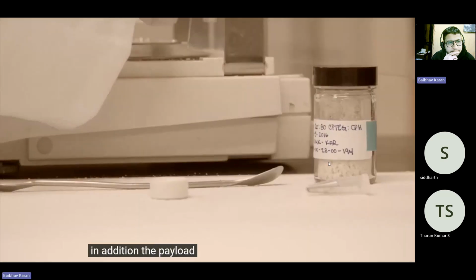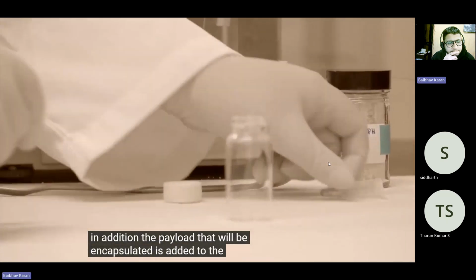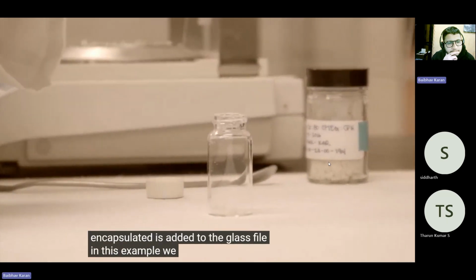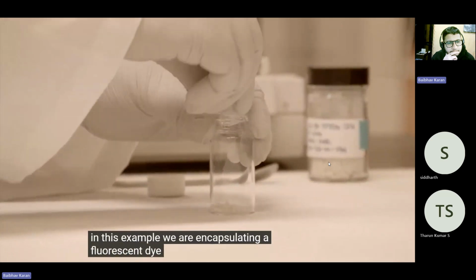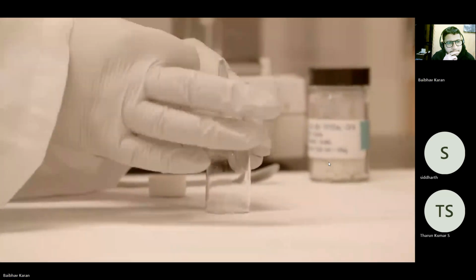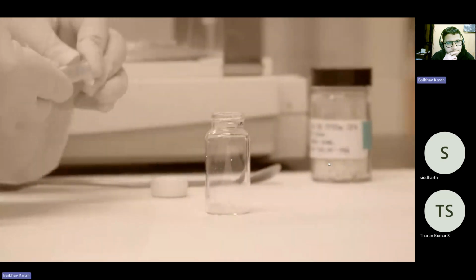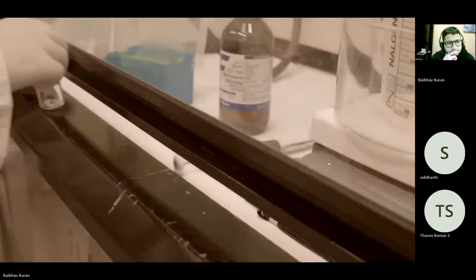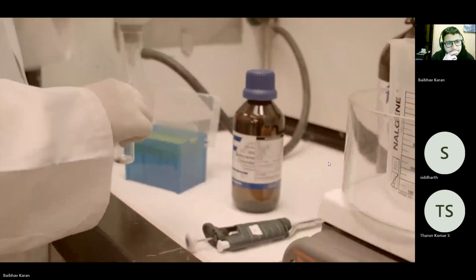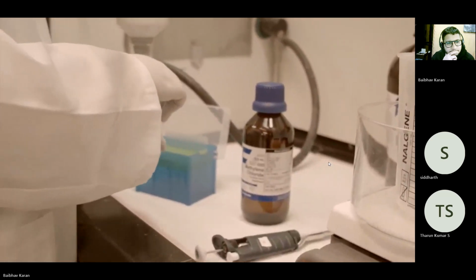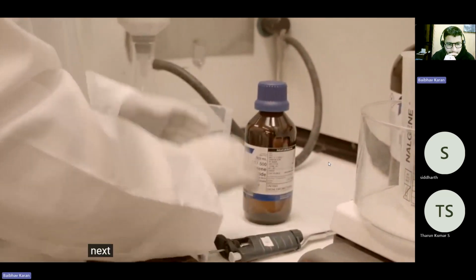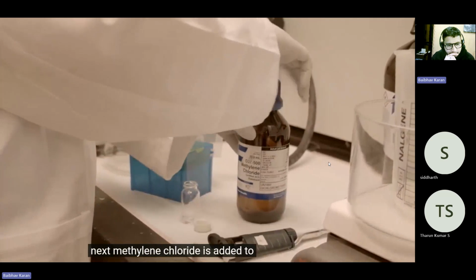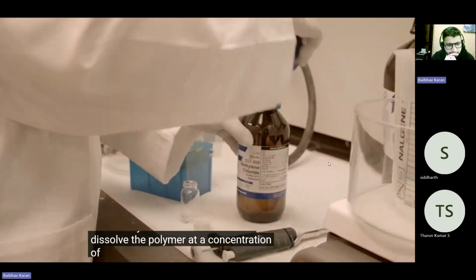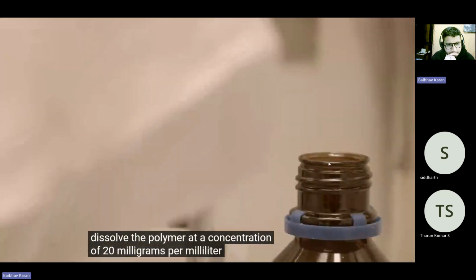In addition, the payload that will be encapsulated is added to the glass vial. In this example, we are encapsulating a fluorescent dye. Next, methylene chloride is added to dissolve the polymer at a concentration of 20 milligrams per milliliter.